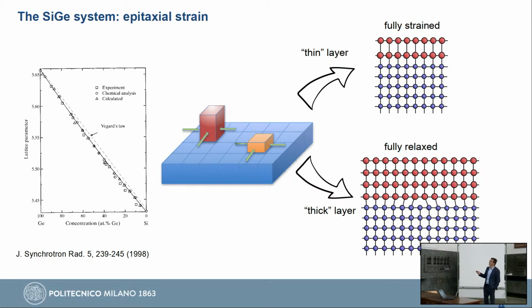If I grow a very thin layer, and we will see later what thin means, I can have a so-called coherent growth. So the germanium will have to adapt to the substrate, and so it will be compressively strained. So we'll have a strain of 4%, which is not small if you think about having, I don't know, an iron bar which is 1 meter long, and you need to press it by 4 centimeters. You need to apply quite some force, and also put some elastic energy in this operation. And so this means that we are actually putting energy in our system, and so this fully strained layer cannot grow infinitely high. At some point, this elastic energy, which I am putting in my system, will have to relax. And this relaxation happens when I go to thick layers and I create some crystal defects.